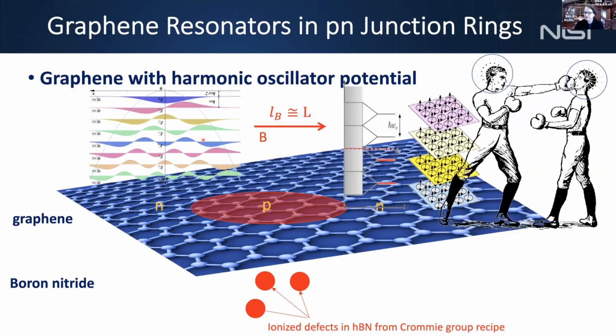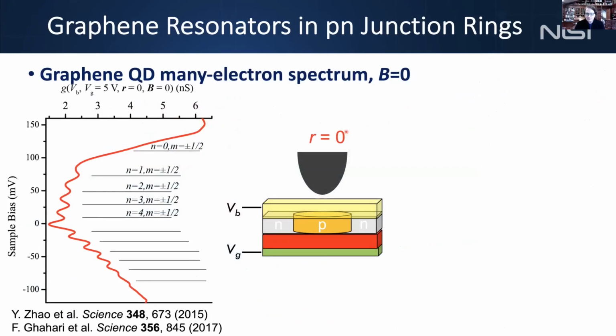Then we're going to turn on the magnetic field, as I said, and we'll see how these evolve into Landau levels and how interaction physics comes into play as we have these highly degenerate Landau levels. So first, let's look at a single spectrum here. I have the probe tip parked in the middle of this p-doped island. I take a spectrum here. This is the bias. This is differential conductivity, and you can see a number of resonances here. So all these resonances are just these quasi-bound resonances of that simulation that I showed you of the dot to begin with. Now, they're special ones because they are taken at the middle. So these are all m = 1/2 states.